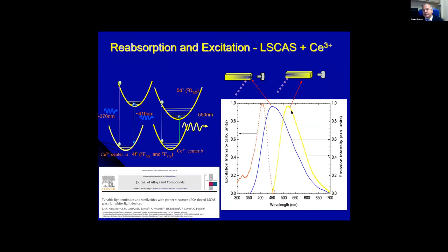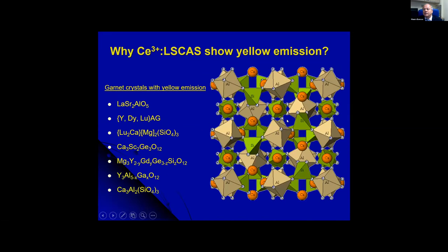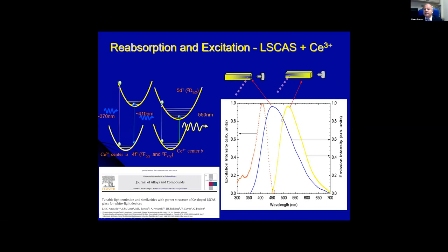Now, this glass also has another important aspect: depending on the position you excite, you get a shift in the emission. You can see here the yellow curve. The center is really in the yellow region, which we didn't find in the literature; no glass could have this kind of emission in the yellow region of the spectrum.